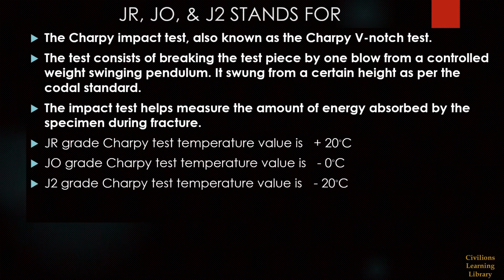Next, we are going to see the temperature value for the particular grades. For JR grade, the Charpy test temperature value is 20 degrees Celsius. For J0 grade, the Charpy test temperature value is 0 degrees Celsius. For J2 grade, the Charpy test temperature value is minus 20 degrees Celsius. Also, we have to note that for these three grades, the minimum Charpy test value should be 27 Joule.